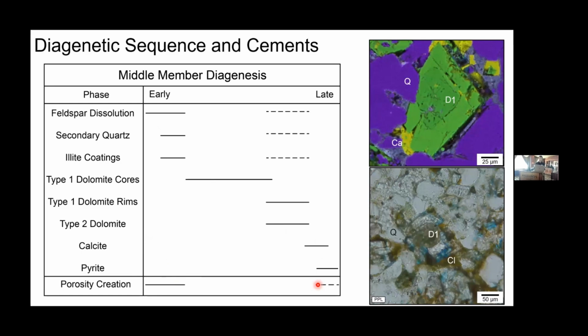So just to give you a preview of what we're going to go through and give you an idea of what these things look like in thin section and EDS. To the top right here is an EDS view of one of these euhedral zoned dolomite crystals, overprinting a quartz grain here. And then similarly in thin section at the bottom, you see exactly the same thing with a dolomite core, labeled D1 here, and an easy to recognize rim around that core, which is obviously a later phase on that earlier form.